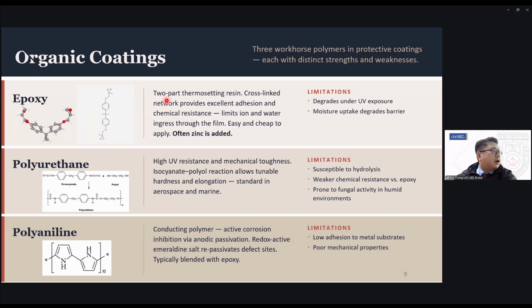There are three types. Actually, there are more than three types, but these are the three most commonly seen in academic literature. You have epoxy, and this is the one I work with most of the time, because it's cheap, it's durable, and it has very good adhesion properties to metal. In the majority of cases, you often see that zinc is added into this epoxy coating, and the reason is that zinc provides galvanic and some kind of barrier protection.